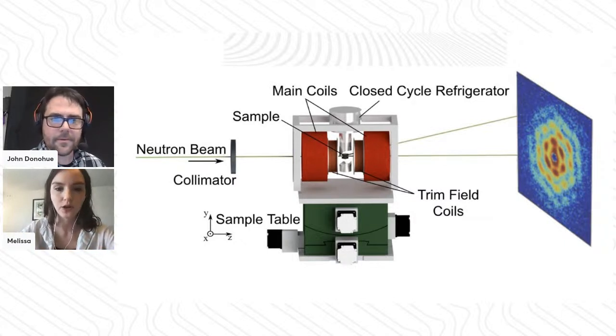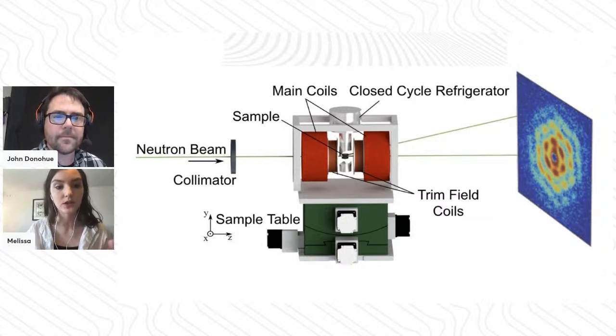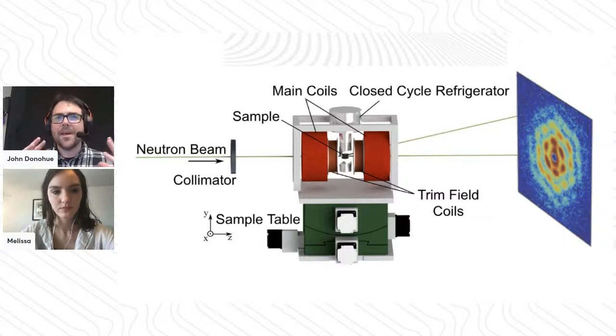That'll help determine the dynamic structures that you're going to be probing, the distances you'll need to achieve, and the collimation - how you're focusing your beam. Those are the main parameters you can control for. Then you can include additional sample environments like magnetic fields and temperature and electric fields that you can stimulate your material with while you're probing with the neutrons.